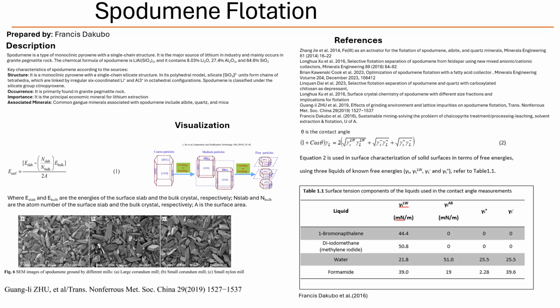The research points to these substituted iron sites being really important active sites for sodium oleate to adsorb onto. So the collector actually targets these impurity spots. It looks that way. And energetically, the DFT calculations show that Fe substituting for Al is the most favorable substitution, which makes sense because iron-bearing spodumene is pretty common geologically. Wow. A tiny impurity becomes a crucial docking point for the collector. That's amazing. What about vacancies, like missing atoms?